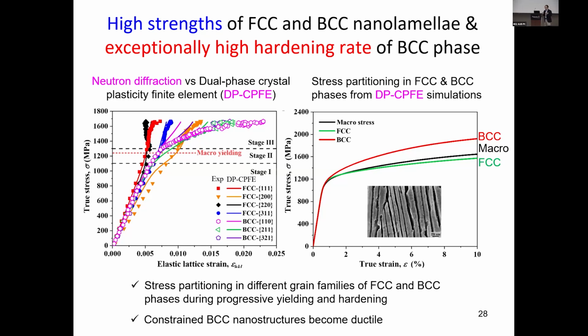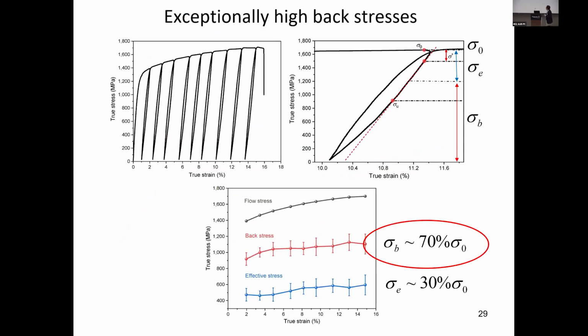As you may know, in typical BCC nanostructures, it's easier to reach high strength because of the smaller length scale, but it's hard to achieve a good tensile ductility. While in this case, the ductile FCC nanolayers really confine the deformation of the BCC nanolayers because of this alternating structure, and enable a very good combination of high strength and high ductility for these BCC nanolayers.